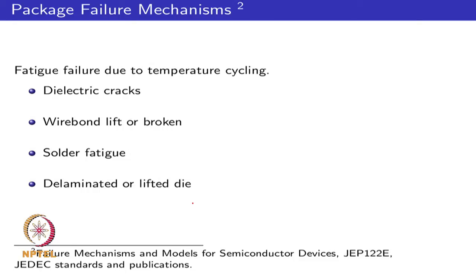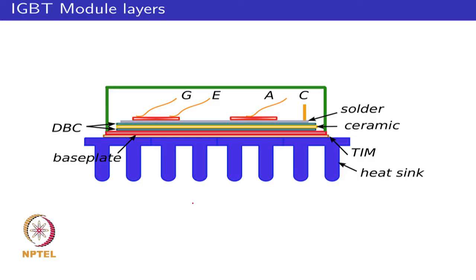If you look at the overall structure of the power module, you have the heat sink at the bottom. A commonly used material for the heat sink is aluminium. You might also use copper if you are looking at higher heat storage capacity. You have your thermal interface material, or thermal grease, between your base plate and the heat sink, which is a thin layer. The base plate is the bottom of your module, which you tighten with screws to your heat sink. A commonly used material for the base plate is copper, or people also look at aluminium silicon carbide, which has a better match with the thermal expansion coefficient of silicon.